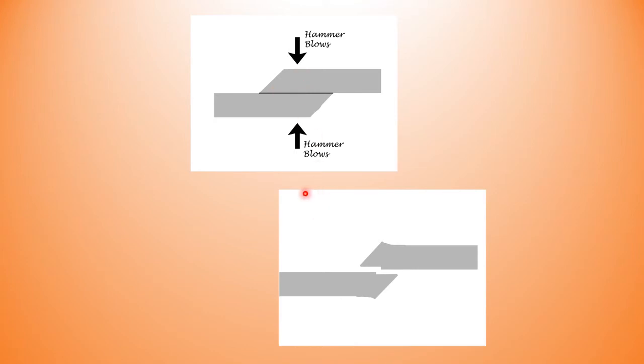By adding another element to your scarf you can ensure your success. You don't want too long of an overlap for these two pieces, so by putting a small step in place you can use that as an index to prevent a long overlap.